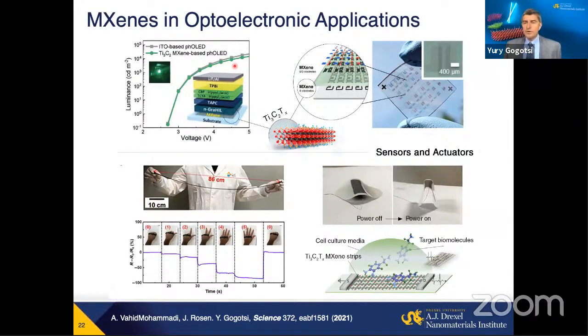But unlike ITO, you can produce it on a surface just from aqueous solution: spin coating, spray coating, self-assembling, dip coating on the surface, and the film is flexible. So you can basically flex it, bend it, twist or fold it, and it will still maintain its conductivity and won't crack, unlike ITO. Printing, conducting substrates, current collectors, again to replace gold and other metals, and do it from aqueous solution.